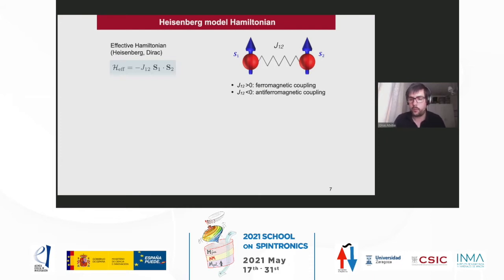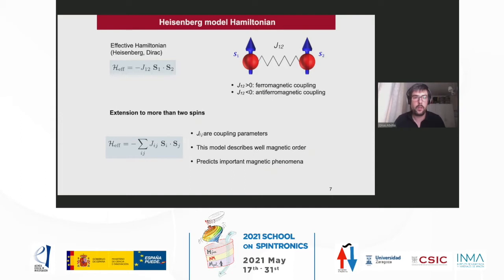This is just for two spins, but one can extend this model to more than two spins, and by summing up over the whole solid or lattice, these Jij are coupling parameters. They can sometimes be calculated from first principle calculations, or by mapping the results from the model to experiments. One can extract sometimes these exchange parameters.